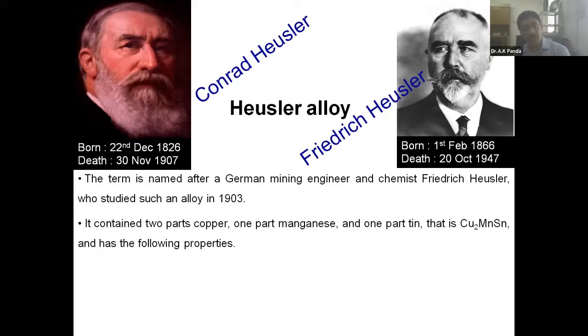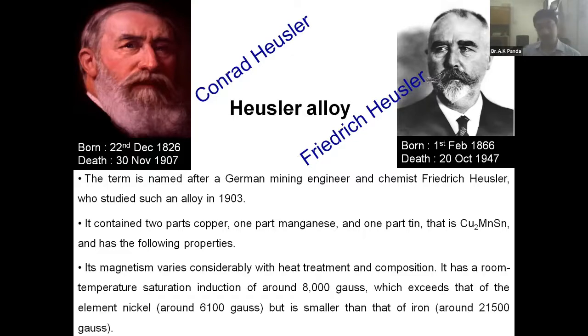It is not only nickel; manganese and gallium came much later. Basically, he found that they named some of the alloys, even two parts of copper, one part of manganese, and tin. They showed very interesting properties. They showed a saturation magnetization of around 8,000 Gauss, that is around 8 kilogauss. Even that is more than your nickel. Of course, it is much lesser than iron, but